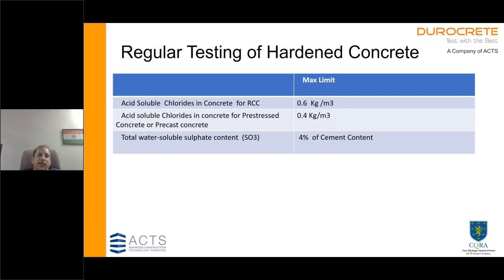Now this is very important. Testing of hardened concrete. We all test concrete for compressive strength, but it is very very important to test concrete for acid soluble chlorides. The maximum limit is already specified in IS 456, which is 0.6 kg per meter cube. And for pre-stressed concrete, it should be 0.4 kg per meter cube.